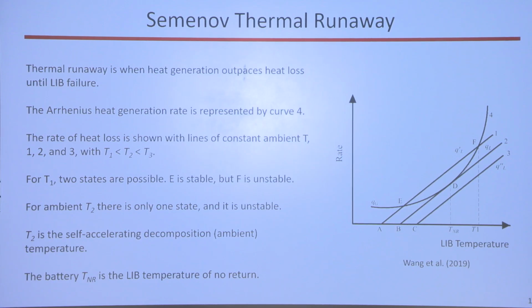It's at condition 1. So condition 1, nice cool room, 22 degrees, and the Arrhenius curve has 2 intersection points on the Semenov curve, intersection E at the lower left and F at the upper right. So right now, we're in a safe state, where line 1 intersects curve 4 at point E. It's nice and stable. If suddenly this battery starts getting a little bit warmer, it'll move to the right, and the heat loss, just the convection coefficient times the temperature difference, will cool it back down. It'll go back to that intersection point E. This is a stable point.